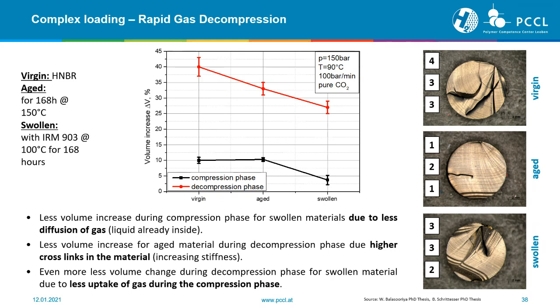And this should show you also that the material behavior is not that easy to correlate. And we should always consider different influencing factors. And in this case, the aged material performance was the best one because of these higher crosslinks, because of the stiffer material performance. However, when we increase the pressure from 150 bars in this experiment up to 200, 300, 400 bars, then it would be in another way and the ranking would also be different.